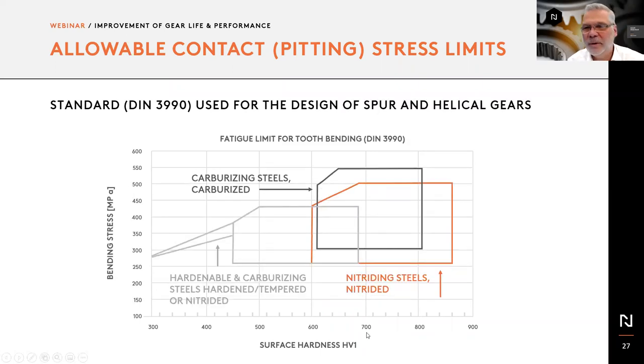But this is also very interesting and goes back to why companies do develop special nitriding steels. When you look at the resistance to bending stress and surface hardness together, specially formulated nitriding steels compare very well with carburizing steels. Of course, we're talking about the better ones like 9310, where you can obtain a much better resistance to bending stress.